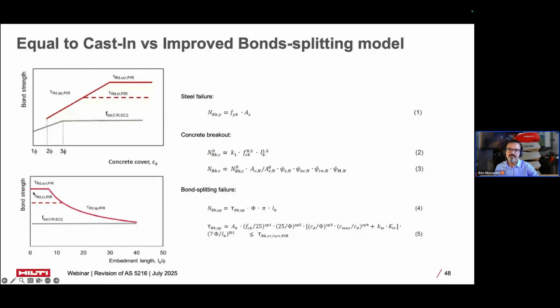But as you can see here, with the new design method, we start with a much higher capacity. And as we go deeper into concrete, we have less capacity. And then this also changes with the confinement. Confinement is the concrete cover or the half of the space between 2 bars. So the more confinement we have, the higher capacity, and it's going to be flat out at some area here.